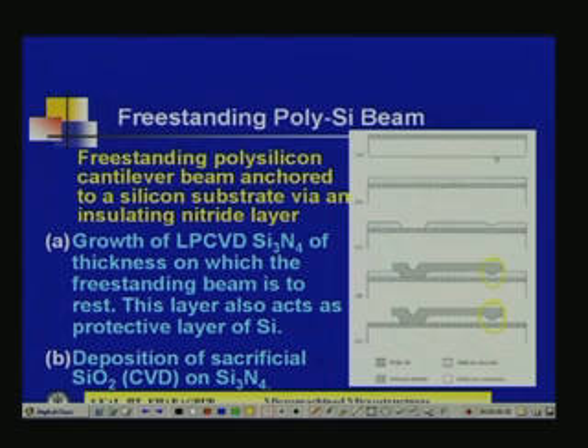So, what are the steps? First you take the silicon. Now, on the silicon, LPCVD silicon nitride of the required thickness, on which the freestanding beam is to rest, is deposited. This is the silicon nitride, Si3N4. Then you pattern this Si3N4, not only the anchor region, but here some dimple is made. You see, that dimple will help. What help?